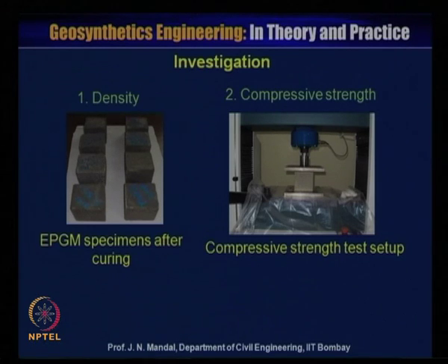Now, we have started this investigation. This is the density of the EPGM geofoam after the curing. Various curing periods were used, maybe 7 days, 15 days, 28 days like this. After this, the test has been performed in a UTM, this is the compressive strength test setup. The sample has been kept between the two plates and then load is applied.